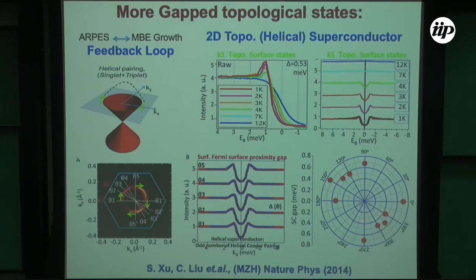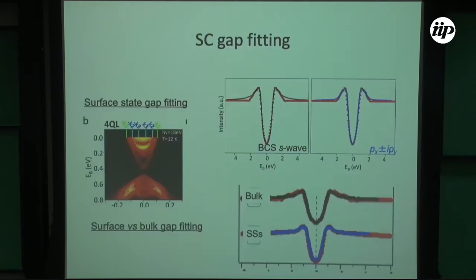So this is telling us that there is a gap and there's no node. Within our resolution, this is just noise, within the error bar. It's nearly isotropic. But what is interesting is that the gap disappeared above TC, so it's not some extrinsic gap we're seeing. We are seeing a gap that is related to the superconductor, because just looking at the spectroscopic data, a gap doesn't necessarily mean it's a superconducting gap. It could be some extrinsic thing.